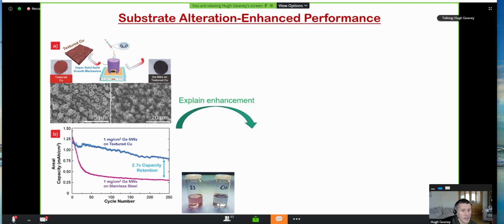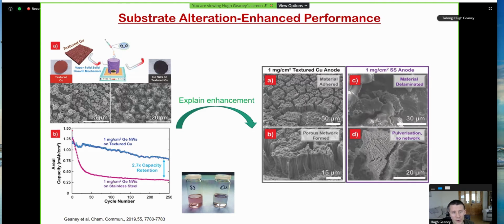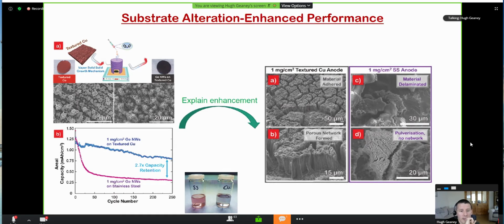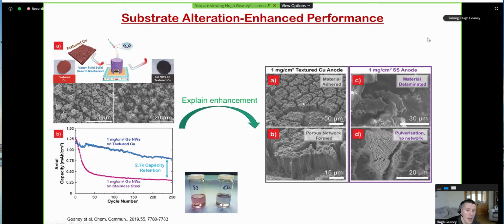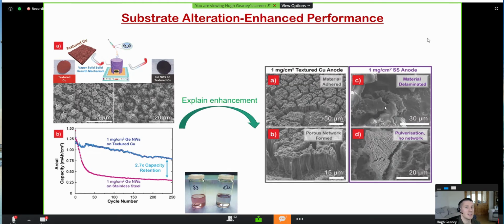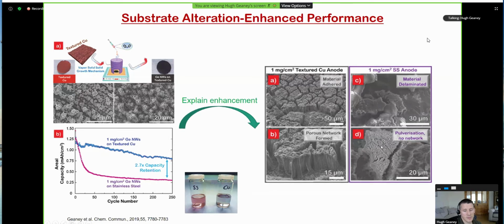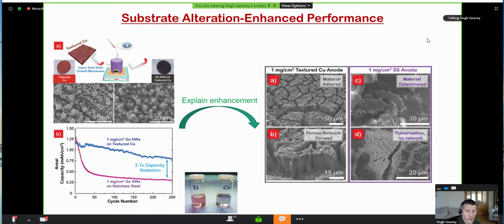So obviously what we needed to do was explain this enhancement. So again, back to the end of the story almost, in terms of looking at the materials and how we can then explain what we've seen. So in this case, on the left-hand side, this is our textured copper anode. And what you've seen is that the material is now properly adhered. We have these large areas of the active material, but also there's porous material formed as well. So you maybe can't see it from this SEM image here, but we did TEM and it had the same kind of characteristic porous network that we would expect for germanium. Whereas in the 1 milligram stainless steel anode, we had complete delamination. Essentially, as soon as we took apart the cell, the material flaked off and there was very little of it actually left. So we had no network formation and pulverization of the material. So you can see that there's a clear explanation at the materials level why the performance is enhanced here.